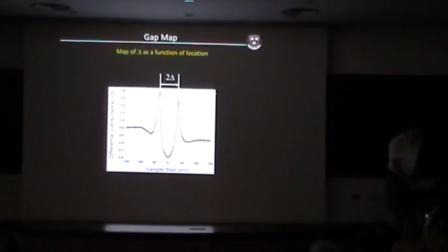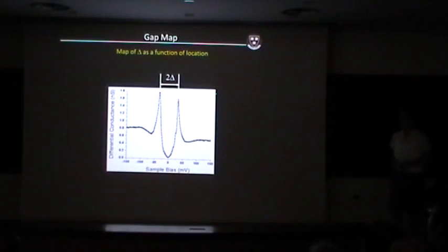Okay. So in order to make sense of the 3-dimensional data, inhomogeneity by reducing this entire piece of information to a single variable, which is the gap, which would take you the distance between the two coherence peaks. There are ways to fit this to analytic forms. There's a Dynes formula, which includes both a gap and a broadening parameter. But in general, the fits fail the common sense chi-squared test.